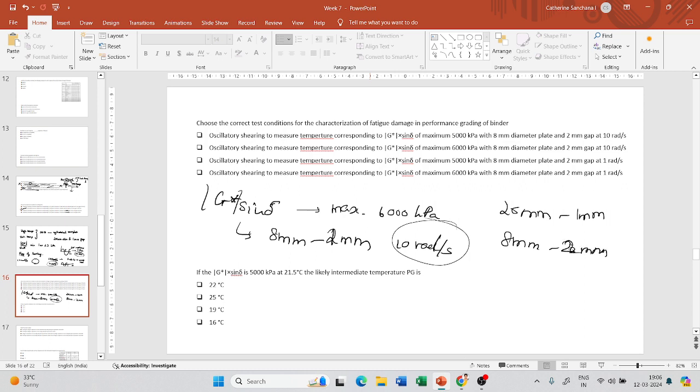For this, let us go back to Galas's lectures, where he said if the material has become stiffer, you should reduce the area of contact of the sample and the plate for many reasons. One is the torque limit of the equipment, right? If the material is going to be very stiff, and if my area of contact is large, then the torque required to twist the sample is going to be large, and there is a possibility that the torque limit of the equipment could be reached.